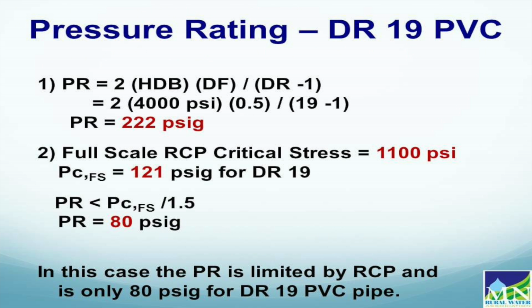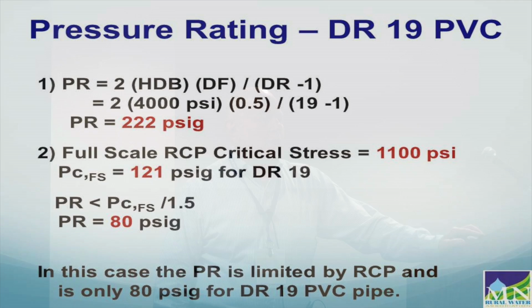If we look at the pressure rating equation, it's 4,000 psi, the design factor of 0.5, or safety factor, if you will, of 2 to 1. That pressure rating is 222 psig. With the full-scale critical pressure of 121 psig, dividing it by 1.5, that indicates a pressure rating of 80 psig. So if we're going to design against RCP from occurring, the pressure rating would have to be decreased from 222 down to 80 psig.